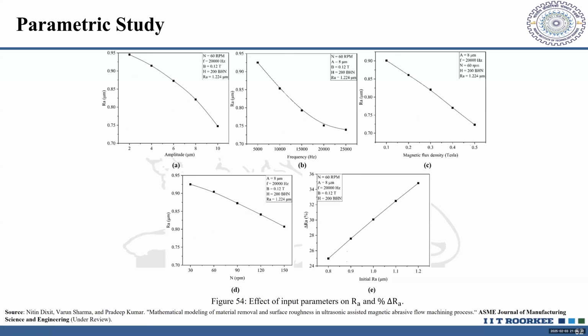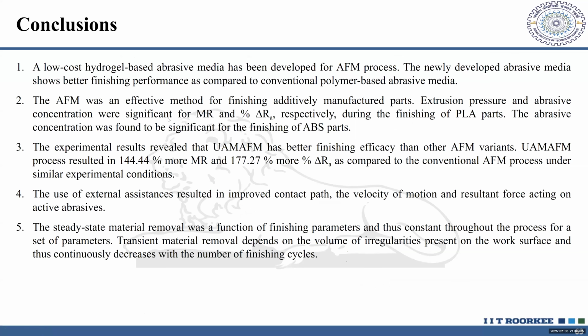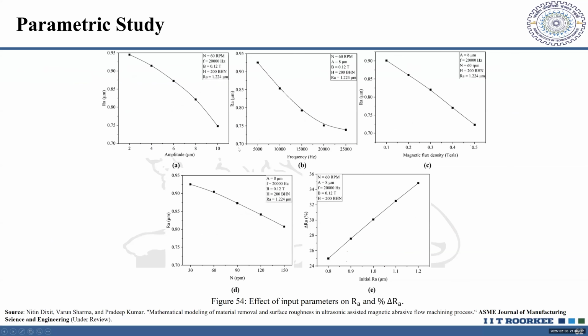Now, similarly is the case for the amplitude of vibration. Now, as the amplitude of vibration is increasing, what is happening? The moment I increase the amplitude of vibration, there is more striking, there is better surface finish. So that is what is being shown over here also, that you can get a surface finish which is of the order of 0.75 microns as compared to 0.95 at 2 amplitude of vibration.